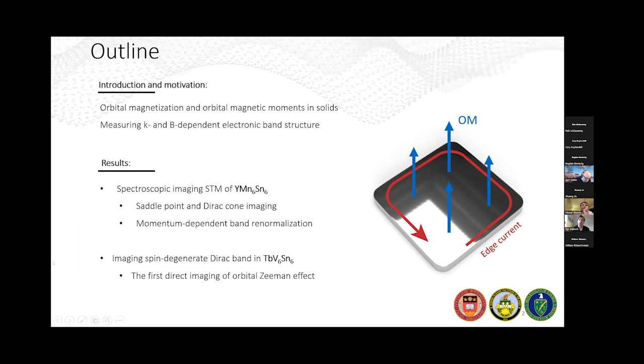The first one is focused on yttrium manganese tin, 166. This is a helical antiferromagnet, at least at low temperature. And what was really interesting to us is that this system turns out to be very nice for imaging the prominent band structure of the Kagome lattice. That involves the van Hove singularity and one of the Dirac cones. So these are very nicely seen in our STM experiments.